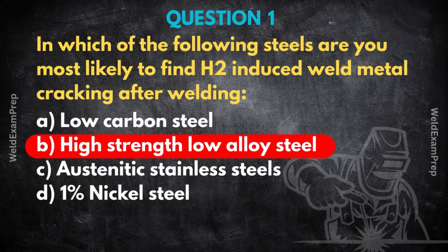It just hammers home why you, as an inspector, need to understand the material's metallurgy to anticipate problems. Knowing this lets you manage risk, maybe specify preheat, choose low-hydrogen consumables, or recommend post-weld heat treatment. Makes perfect sense. Okay, so from understanding hidden weaknesses in the material, let's talk about actually finding defects, especially those lurking inside the weld. Question 2.